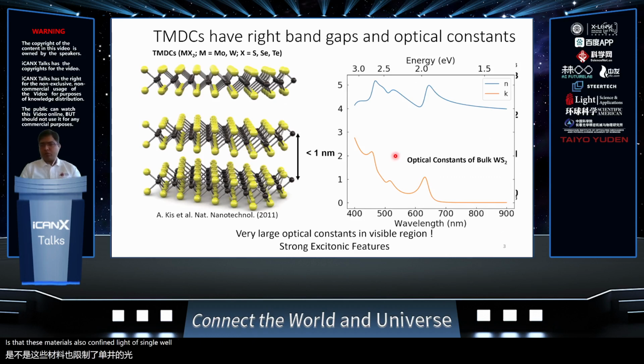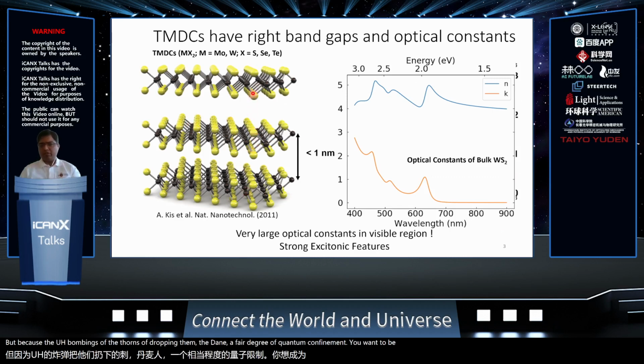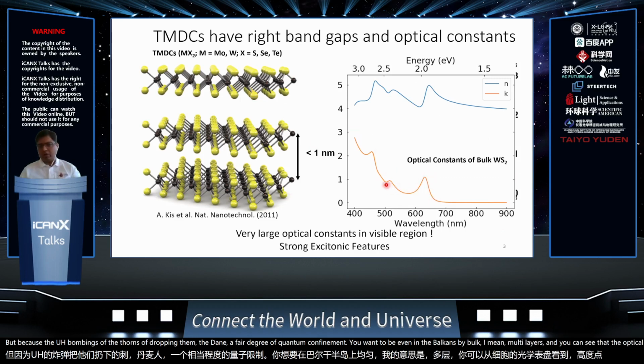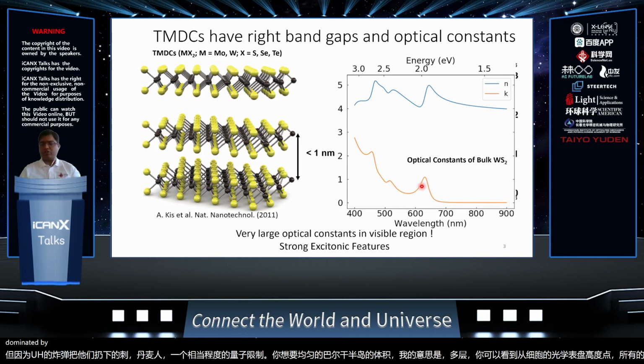Here, what I'm showing you are the optical constants of bulk WS2. Now, you would expect that typically in bulk cases, like you have in III-Vs, excitons don't dominate the optical response. But because the bonding structure is so anisotropic, they retain a fair degree of quantum confinement, even in the bulk case. By bulk, I mean multilayers. And you can see that the optical dielectric function is still highly wavy, or dominated by excitons, over here.